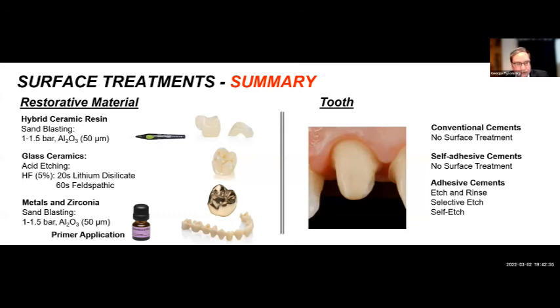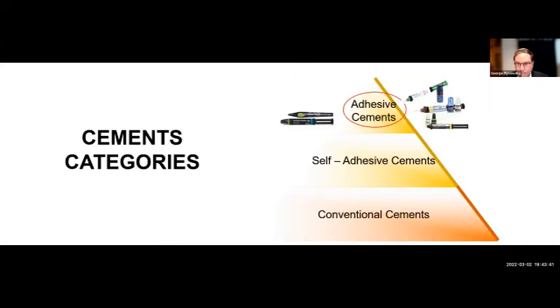So in priming the restoration, we either hydrofluorically etch, or we prime chemically some of the high strength materials, or we sandblast the weaker resin type of materials. On the tooth, on the right-hand side of the slide, on conventional cements, we really just clean the tooth. We can pumice it and clean it up, but we really don't treat the tooth because it's going to be conventionally cemented. Same thing for self-adhesive cements, because they have a primer built in that can penetrate into the tooth structure. And on the adhesive cements, we use our total etch or typical adhesive procedures. We can total etch and rinse, or we can selectively etch only the enamel and not the dentin, or we can do a self-etch pattern where we can bond the entire restoration to the tooth structure. Okay, so those are the areas: interface dynamics, tooth, and restoration.